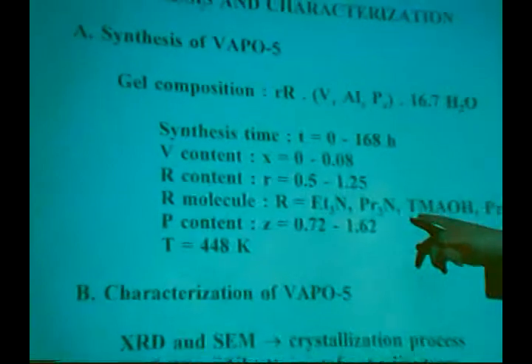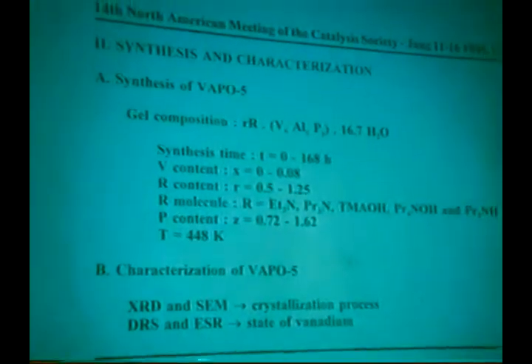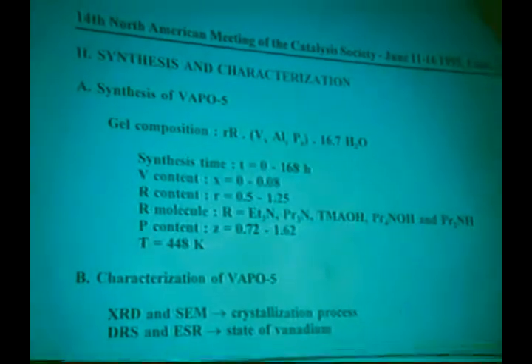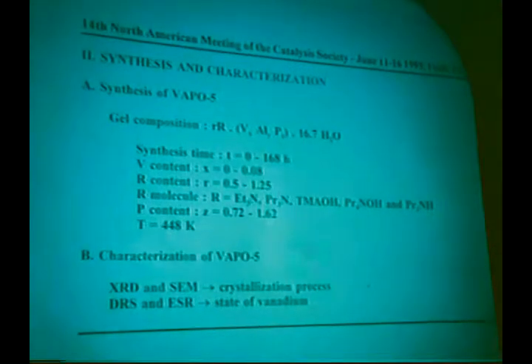All materials were synthesized at 448 K. As templates, we have used triethylamine, tripropylamine, tetramethylammonium hydroxide, tetrapropylammonium hydroxide, and dipropylamine.